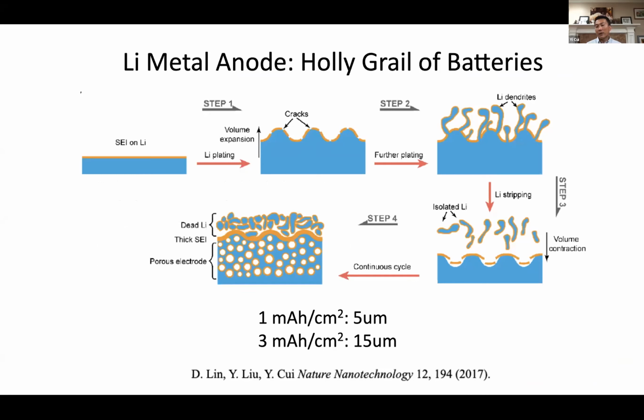Lithium metal doesn't carry heavy hosts. If it's pure lithium metal, you don't have a host, and the energy, gravimetric and volumetric, are all very attractive. However, plating lithium through this plating and stripping process during charging and discharging is very hard to control because you don't have a host. In the plating, you lose control, and you cause surface curvature change and cracking of the solid electrolyte interface, causing hot spot formation. This can shoot out filamental structures, oftentimes in the form of dendrites. Dendrite is dendritic, right? This branching structure. Sometimes it has branching, sometimes it's not. People start to mix up these terms.